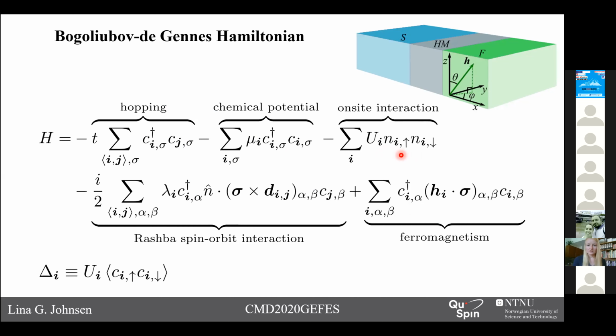The superconducting on-site interaction is treated by a mean field approach, where we solve for the superconducting gap delta iteratively. The Rashba term has a strength lambda and a direction n perpendicular to the interface, and here sigma is the vector of Pauli matrices and d is a vector from lattice site i to lattice site j. The ferromagnetic term has an exchange interaction h, which is also shown in the model figure as a green arrow.